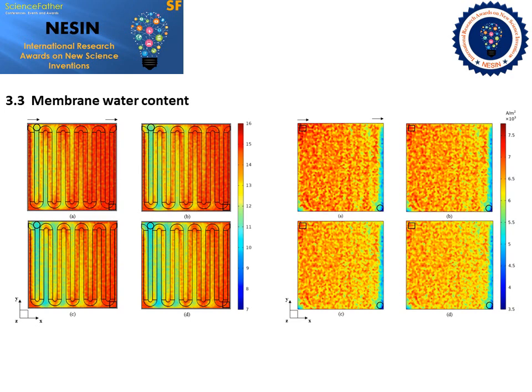It is found that with the increase of TCR, the current density on the membrane shows a trend of becoming smaller, and the circle box on the figure represents the area with the smallest membrane current density, and the rectangular box represents the area with the largest membrane current density.